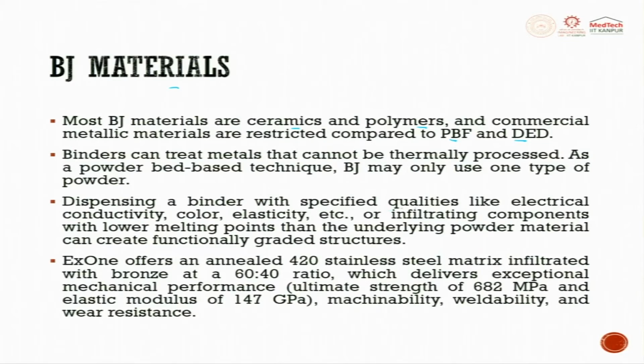Dispensing a binder with specific qualities like electrical conductivity, color, elasticity, etc., or infiltrating components with a lower melting point than the underlying powder material can create functionally graded material. This is a challenge, but people have started doing it. ExOne offers an annealed 420 stainless steel matrix infiltrated with bronze at a ratio of 60-40, which delivers exceptional mechanical performance, machinability, weldability, and wear resistance.